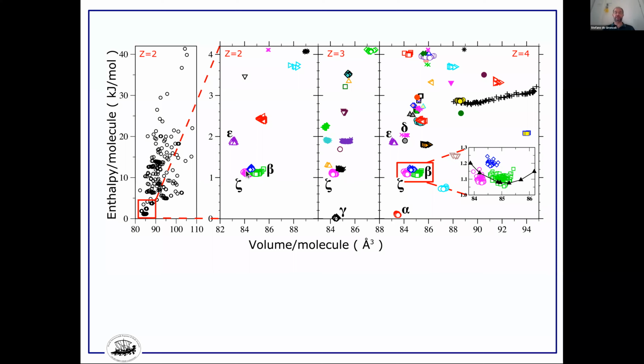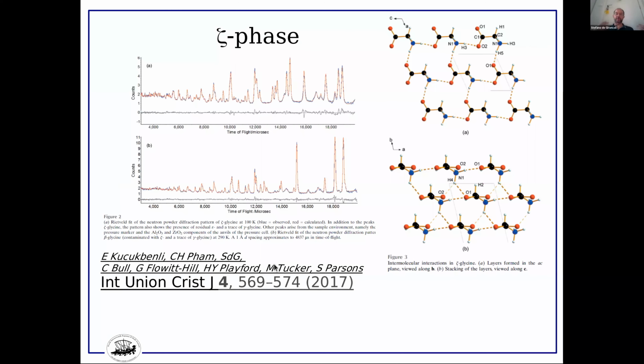It was a structure that was not previously identified. And we proposed that this is indeed the structure that is obtained when you remove pressure from the epsilon phase. There was an experimental group that had some unpublished data about this unknown structure. By comparing our proposed structure with their experimental data, through a structural fit, they obtained a very good agreement, and so it was confirmed that the structure that we discovered with this USPEX calculation is indeed the zeta phase of glycine. Okay, this is what we could do.